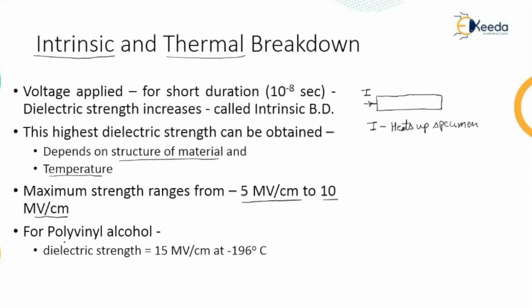For example, polyvinyl alcohol has a dielectric strength of 15 megavolt per centimeter at negative 196 degree centigrade. So the maximum electrical strength which is recorded for this particular solid medium is 15 megavolt per centimeter.